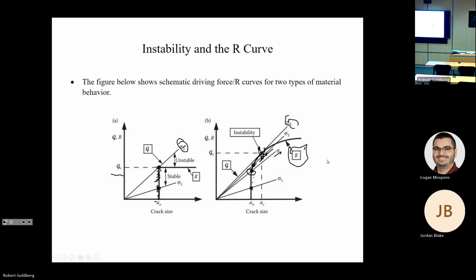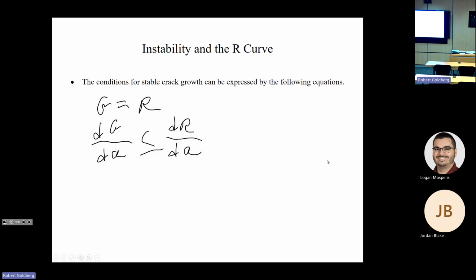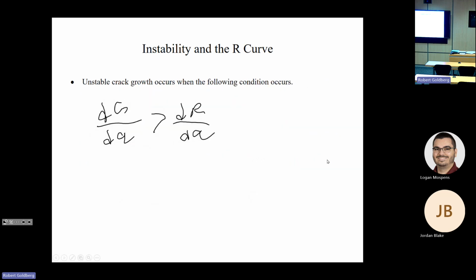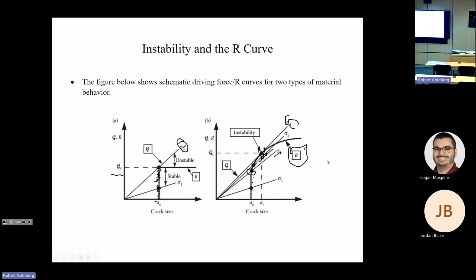So by this equation, we say that unstable crack growth occurs when the rate of change of your strain energy release rate is greater than the rate of change of your resistance. However, this point of tangency, the point where it becomes tangent, depends on the shape of your driving force curve. So it depends on the shape of your strain energy release rate with respect to crack size, and that depends on the configuration of your structure.